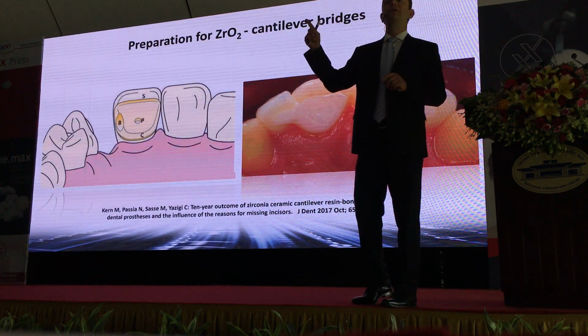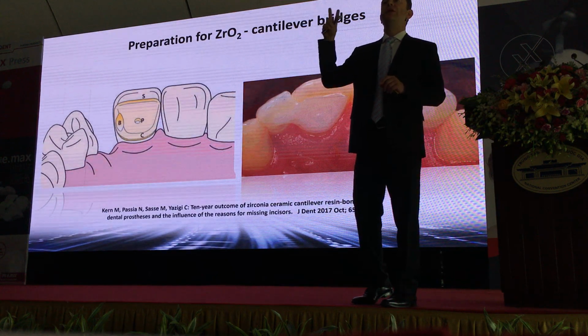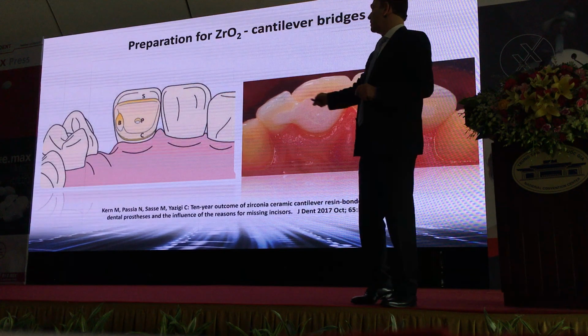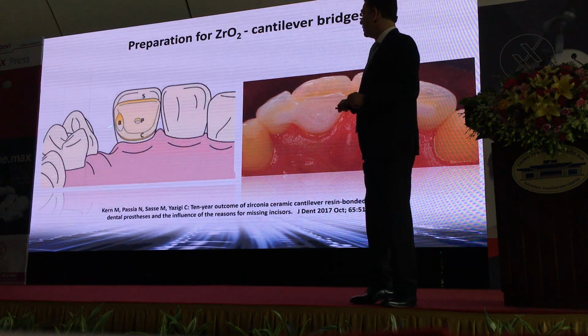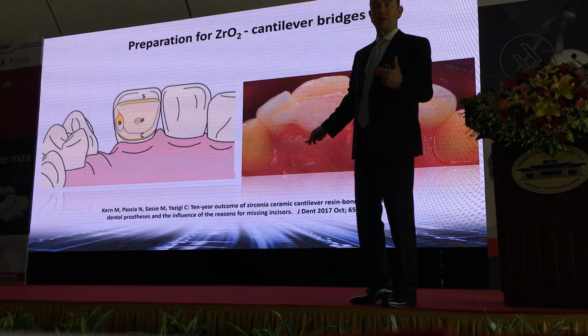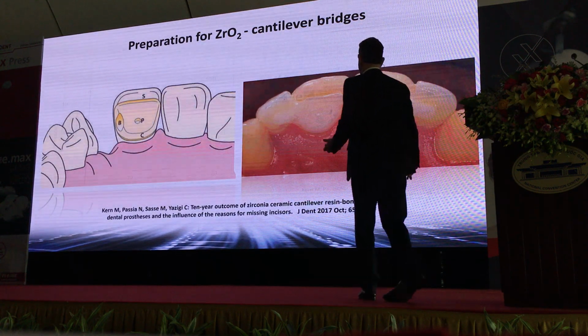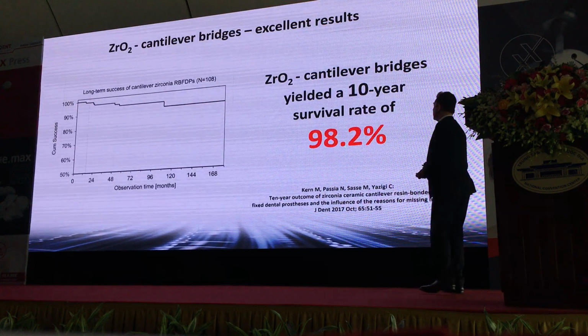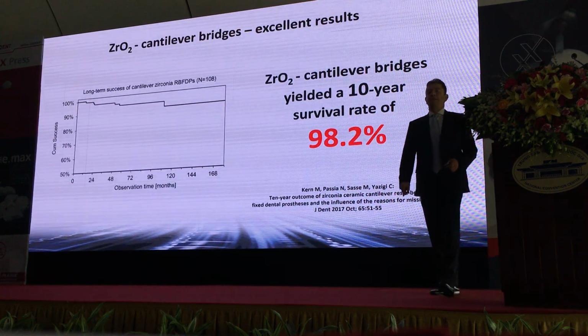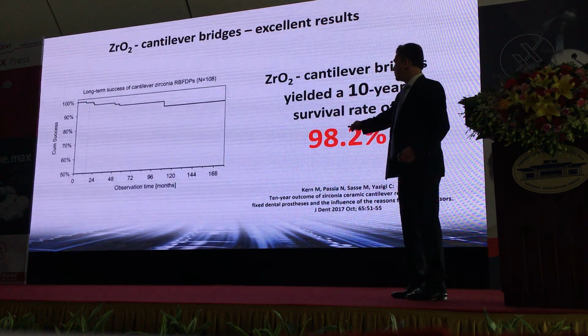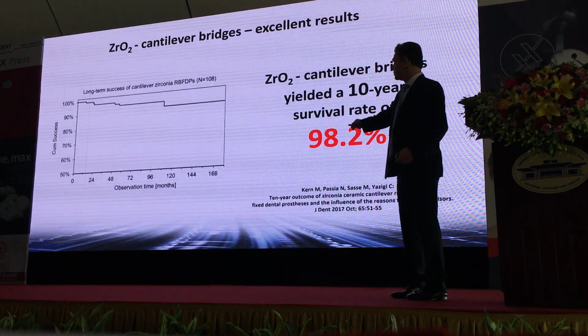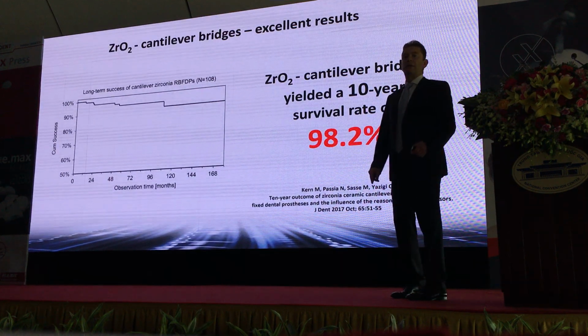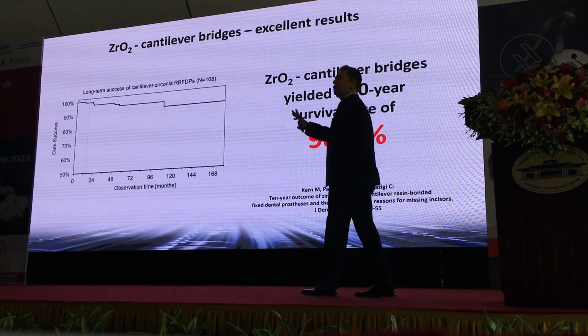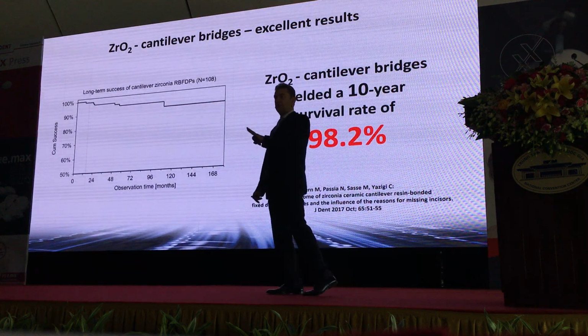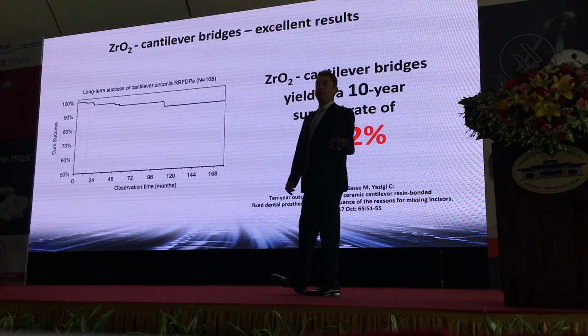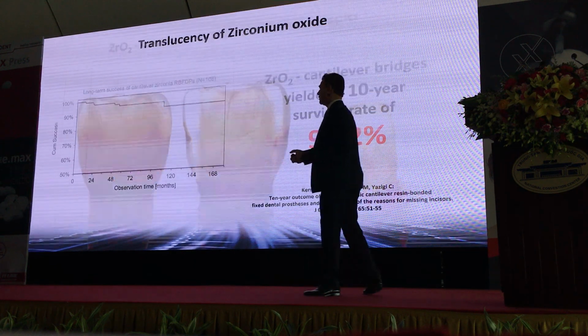And by the way, one-wing cantilever is much more successful than two-wing cantilever. Okay? So don't put a cantilever on both sides here. Only one is fine. It's a better outcome. It has been researched. And you can see after 10 years, the survival rate is 98%. Very good. After 10 years, 98% success rate. Very good success. So for some indications, you need to use zirconia because you cannot do it with other ceramic material. So this is one of the indications which is, I think, very good.